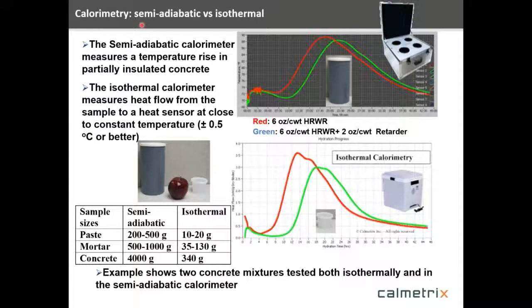So basically, we've got these two different types of devices, the semi-adiabatic and the isothermal. Semi-adiabatic devices, as I mentioned in the previous slide, we measure a temperature rise within a partially insulated container. These are qualitative devices, versus the isothermal device, where we control the temperature around the sample, and we measure the heat flow as a function of time at whatever temperature we're running the experiment at. And these are considered quantitative devices.